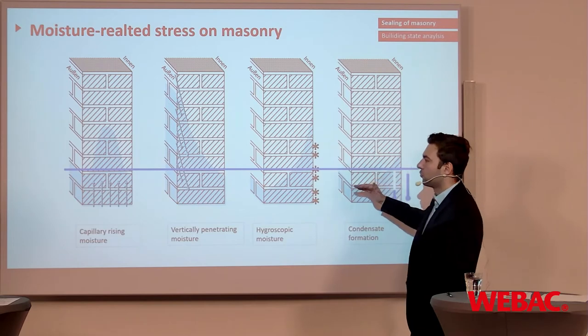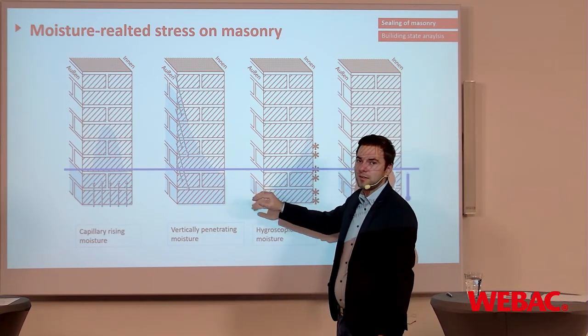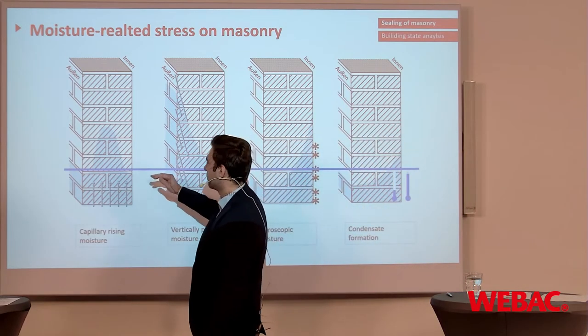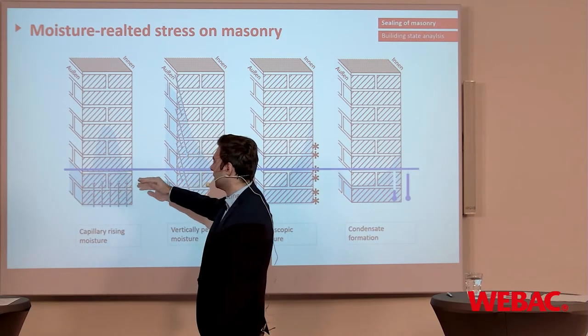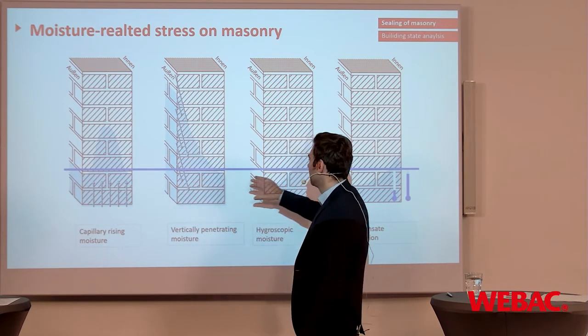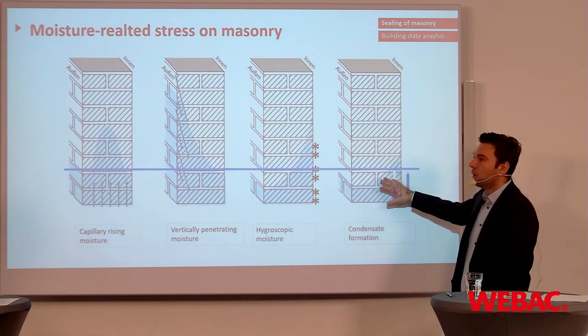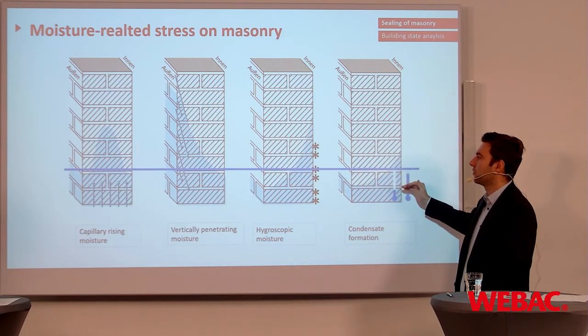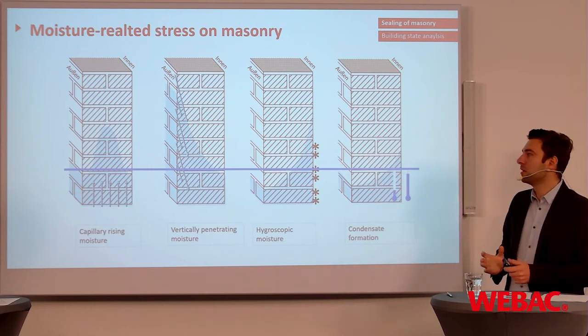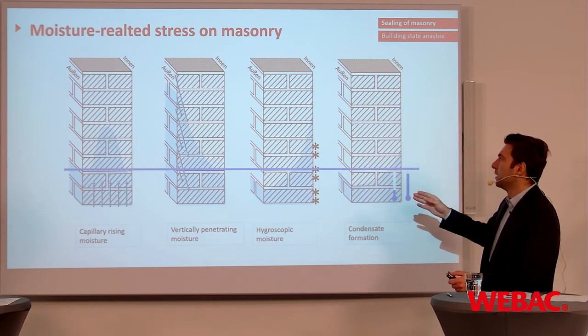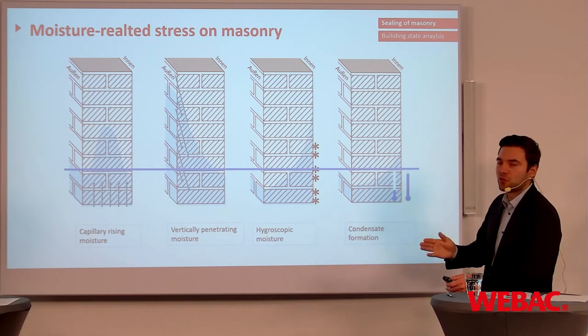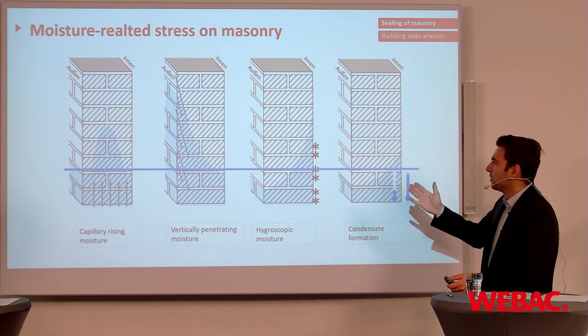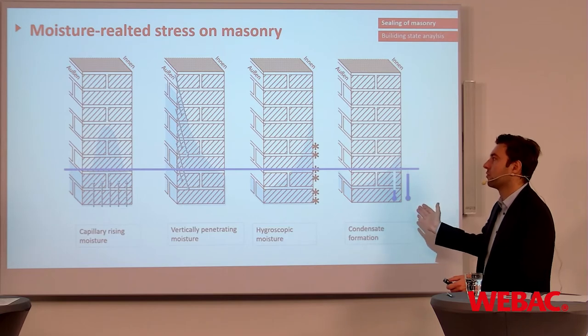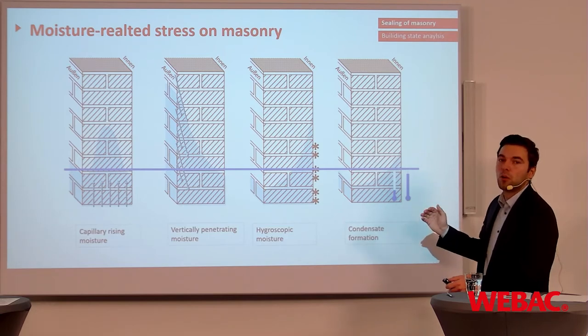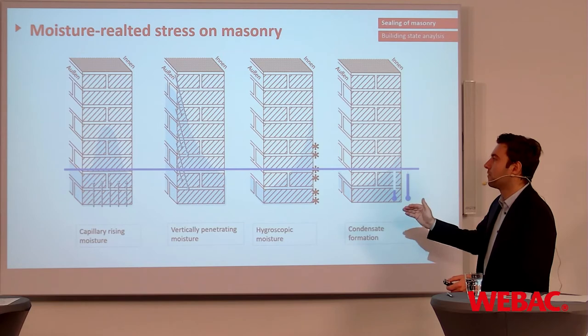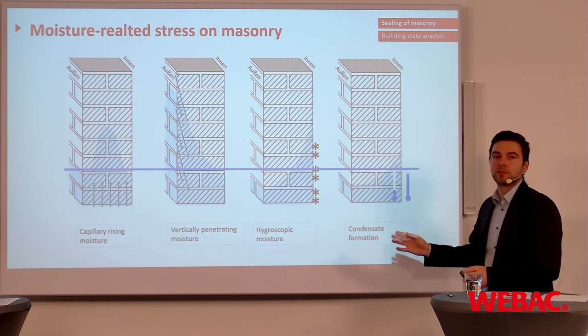We just want to make sure with this line, as you maybe can see, that the damage from the inside is looking more or less the same with every type of moisture-related stress. So the damage inside your structure may look the same even if you have different kinds of stress that cause trouble to your construction. Therefore you need to make sure what kind of stress you have prior to carrying out the injection.